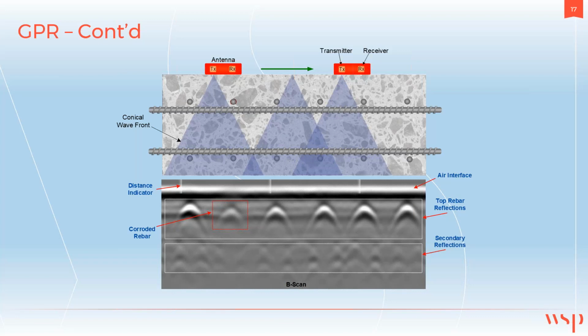So for example, if the antenna is scanning across the surface from left to right and encountering the reinforcing bars that are embedded, the signal that you see in what we call a B scan, which is a vertical cross section in the direction of the scan, results in the bars showing up as these parabolic features, where the contrast from white to black in this rendering indicates the change in dielectric at that location. The higher the amplitude of the reflection, the darker the contrast.